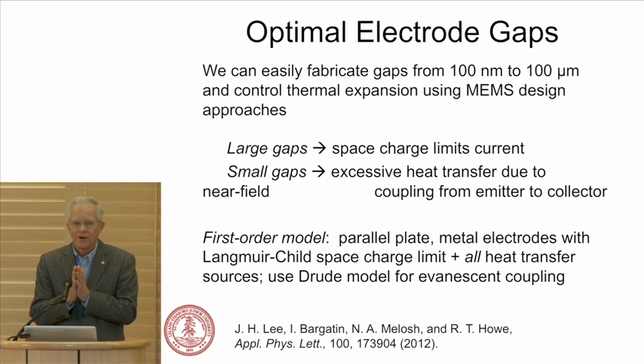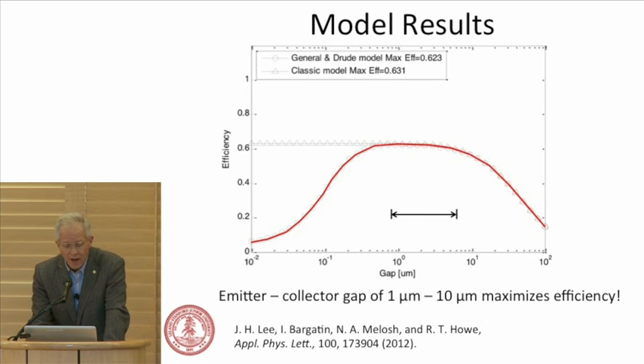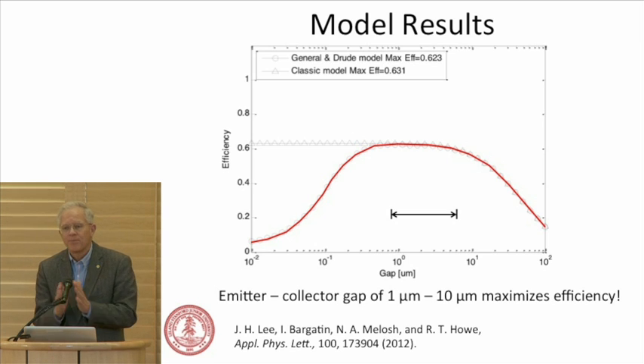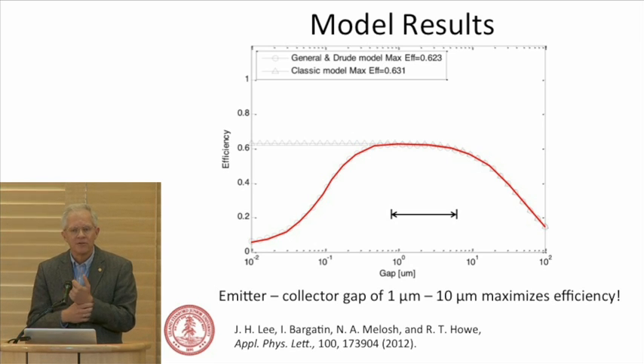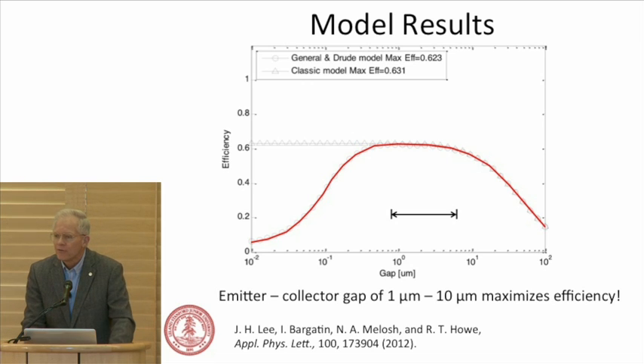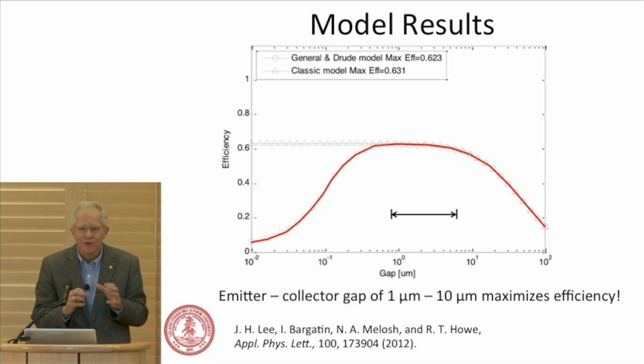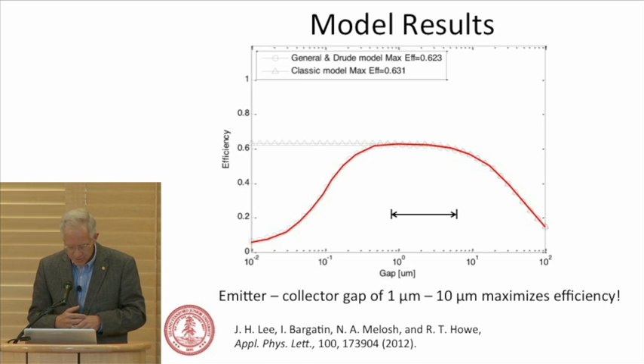We can make gaps using MEMS technology well below a micron. Is that desirable? Turns out that you have these near-field heat transfer effects and you get thermal shorting, so there should be an optimum. And Murphy must have been asleep, because the gap of 1 to 10 microns is something that is like falling off a log for people making gyroscopes and accelerometers, which I spent a good part of my early career on, silicon gyroscopes and accelerometers using MEMS technology. So in fact, that's great.